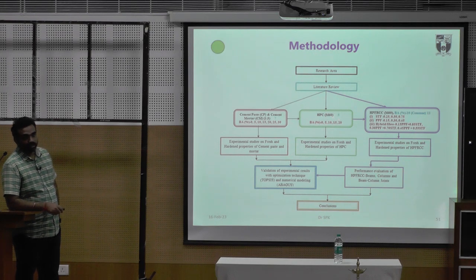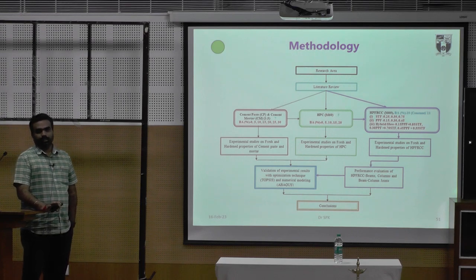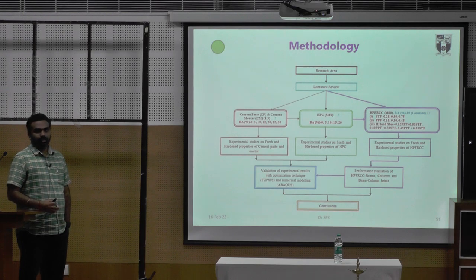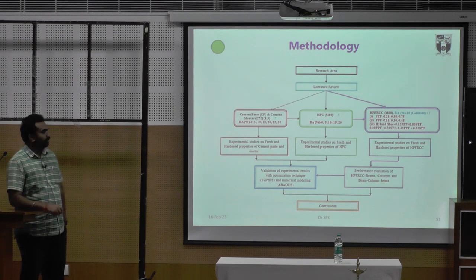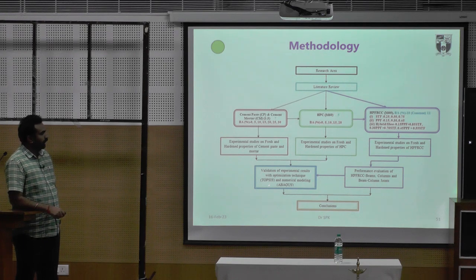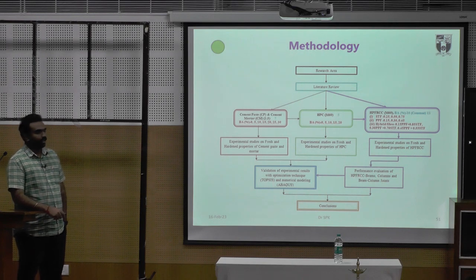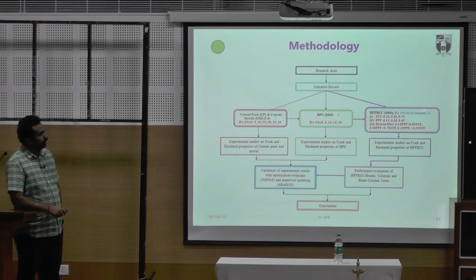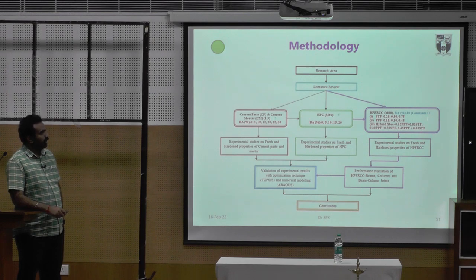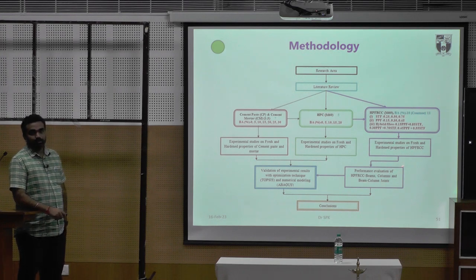We conducted experiments for fresh and hardened properties of HPC. We found that 15 and 25 percent are not suitable, and 10 percent is the optimum percentage. People questioned how we give solutions based only on experiments, so we also used optimization techniques like Taguchi-based TOPSIS method and Analytical Hierarchy Process. Based on that, optimization was carried out and similar results were identified. Keeping 10 percent as constant, we varied steel fiber, polypropylene fiber, and hybrid fiber for HPFRCC.